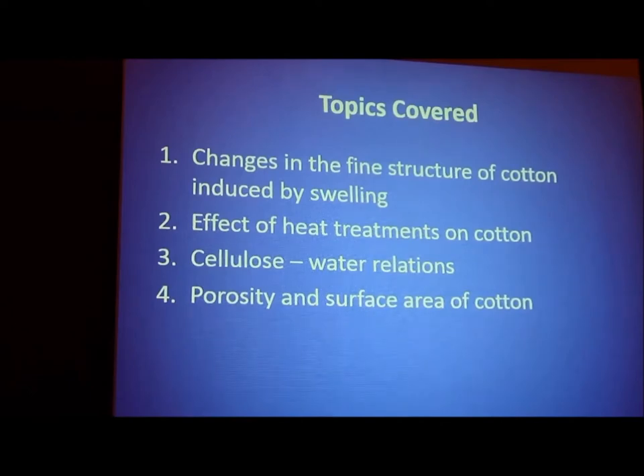However, while the cellulose 4 form was known to exist, nothing could be deduced about fiber properties, since at that time it was thought that conversion required heating the cellulose at high temperatures such as 260 degrees centigrade, in glycerol. Under such conditions, the fiber structure degraded. Also, the mechanism by which cellulose fibers fractured under tensile stress needed further elucidation.